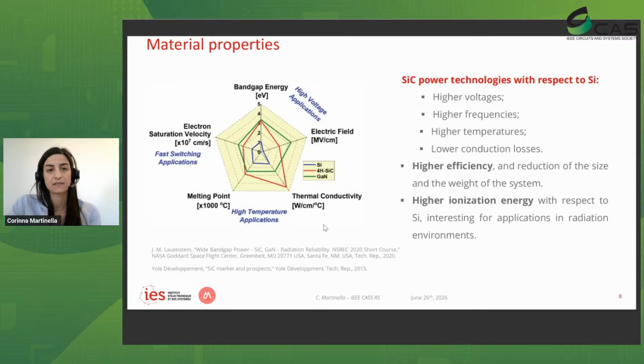This material has some specific properties which make it interesting for power devices that can indeed improve the figure of merit I just presented. So we have a wide bandgap material, so we have a large bandgap. And also this material can sustain a 10 times higher electric field with respect to silicon. So overall, this means that in order to sustain the same electric field, now you can manufacture the device with a 10 times thinner epitaxial layer. So overall, you are reducing the thickness of your epitaxial layer, and in turn, you're also reducing your on-state resistance. And that's why your figure of merit improves.